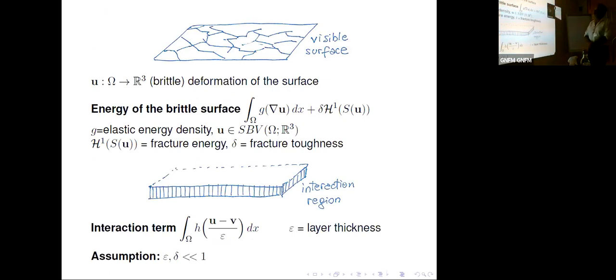On the visible surface, partially visible surface, you see also a pattern of cracks. So you have a deformation of the surface which allows for discontinuity. So it's a brittle deformation. It's sufficiently smooth outside an array of cracks. The array of cracks can be thought of as the set of discontinuities of this deformation. So that's why we have this S(u) here. And the energy is the elastic energy of the surface where it's not broken.